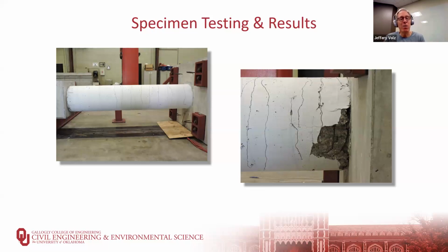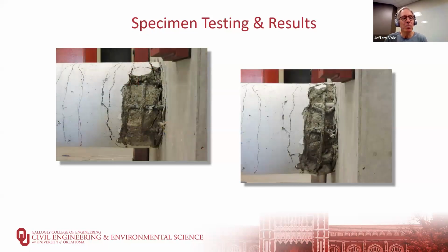We get more cracking, and what typically happens in a test like this for reinforced concrete, you start to spall the cover off because there's nothing holding the cover on other than tensile strength of the cover bonded to the concrete on the inside. So it's very typical to start spalling off the concrete. On the left, more cycles.